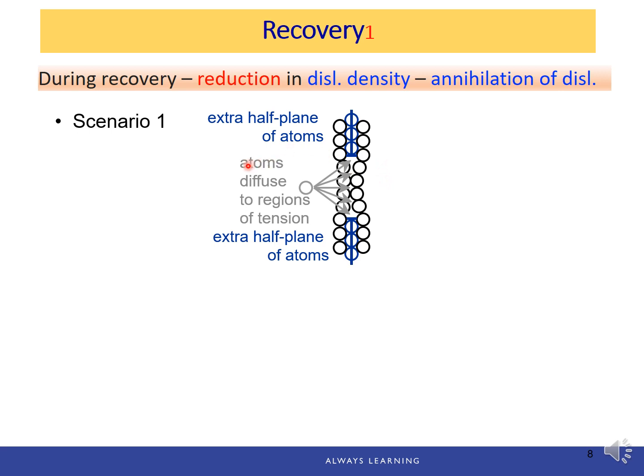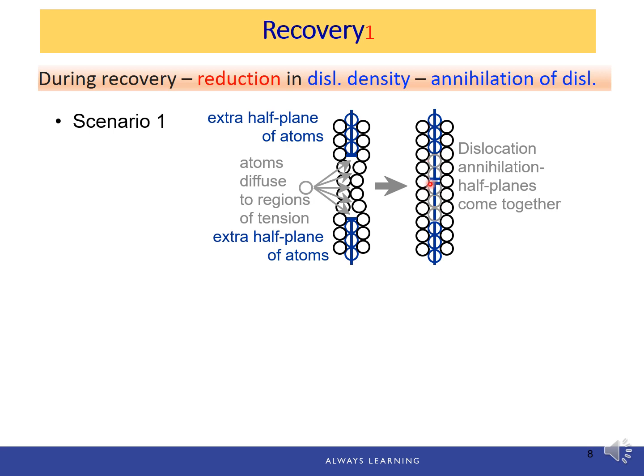So because of the elevated temperature, atoms will diffuse to the region of tension and go into those spaces. As a result, the half planes come together, or the atoms will fill into the gap, so there's no more actual half plane of atoms. So we have 3-4 rows of atoms, and there's no distortion within the lattice structure or crystal structure. So this means the dislocation disappeared, and we call this dislocation annihilation.